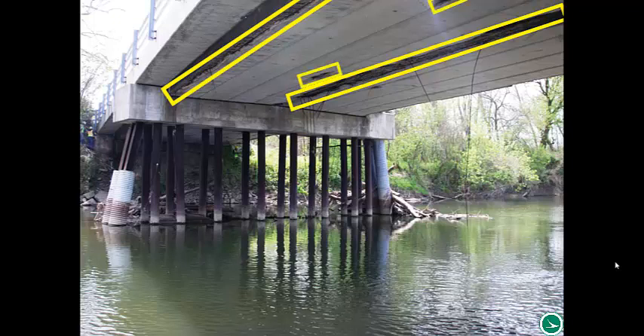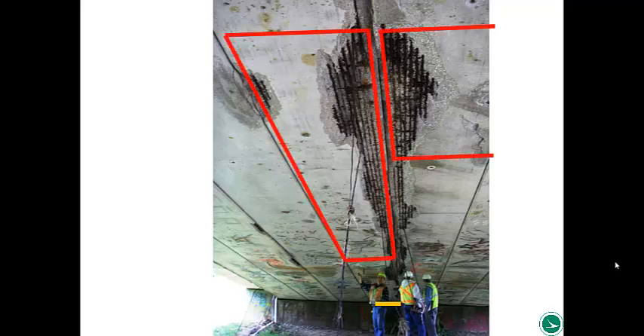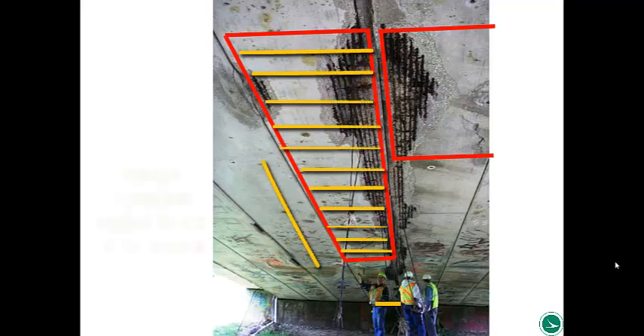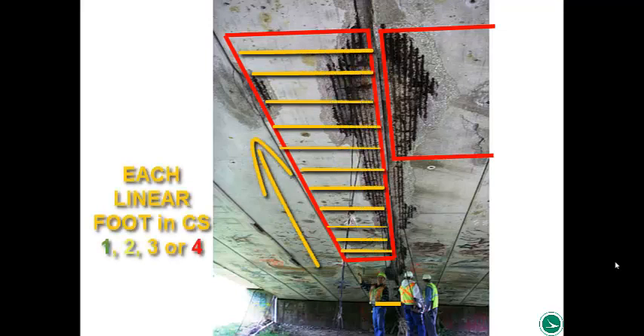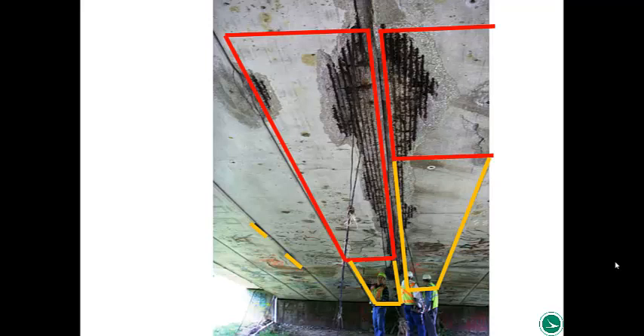Here are some other locations of exposure. Even if strands are hanging down and visible, we treat them all as exposed — as not doing the heavy lifting. Span two was the middle span; span one had the worst, or more, exposure. The red box here indicates portions where more than a quarter of the cross-section is affected along that linear foot. Each linear foot in those areas would be placed in condition state four. Other portions would probably remain in condition state three, though even one linear foot in condition state four triggers a structural review or analysis.